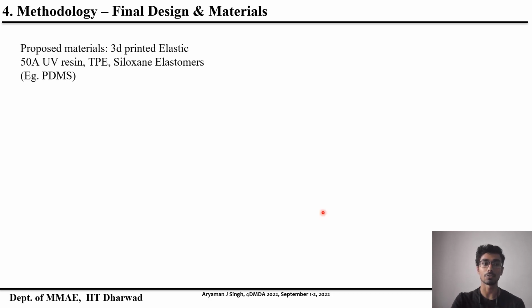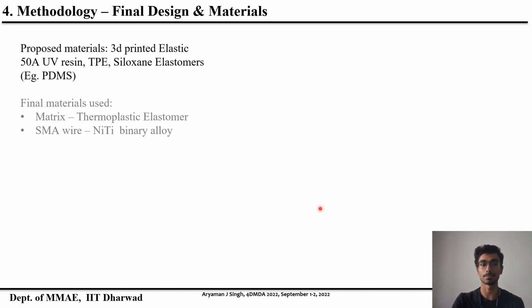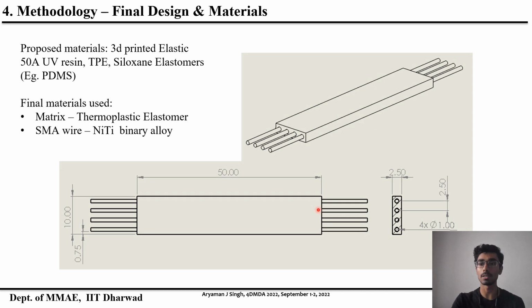As discussed in the previous slide, the matrix should be soft and flexible, for which the proposed materials were 3D printed elastic 50A UV resin, TPE, which is thermoplastic elastomer, and siloxane elastomers such as PDMS. The final material used was thermoplastic elastomer because of its ease of 3D printability. Our aim here was to use 4D printing to develop the actuator instead of creating a mold of siloxane elastomer as a matrix, which was the case in the published literature.